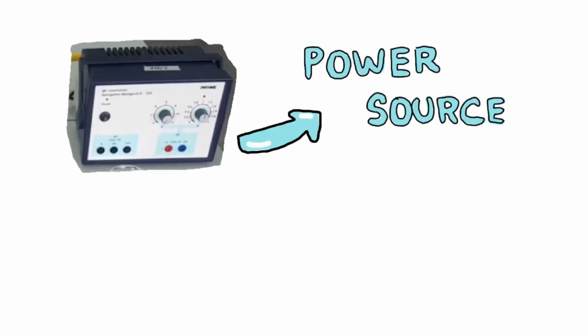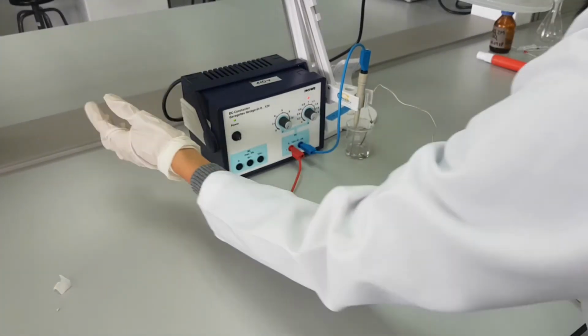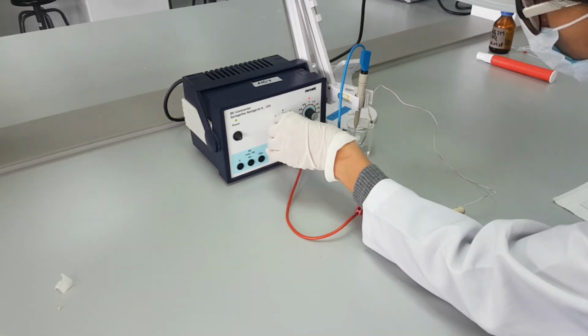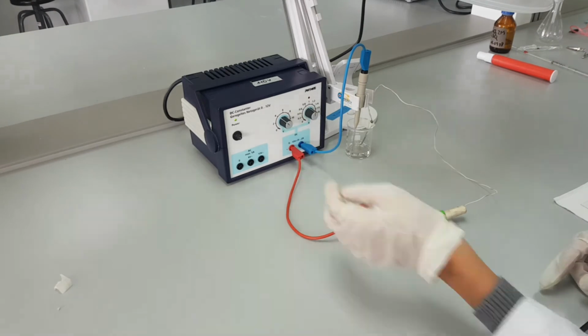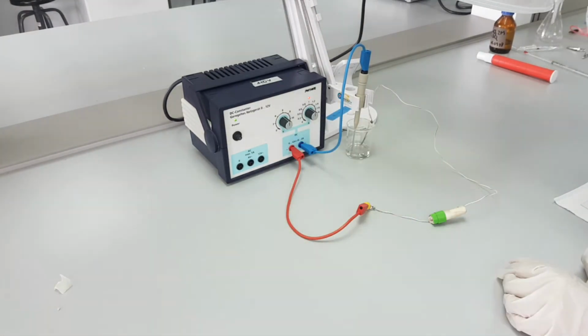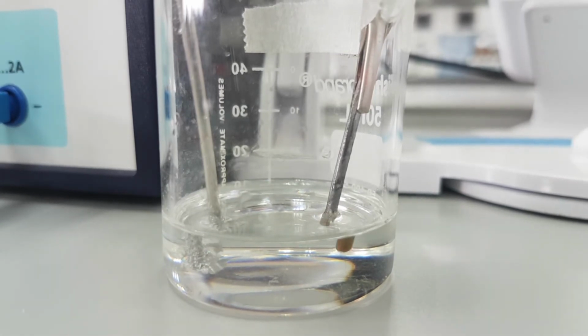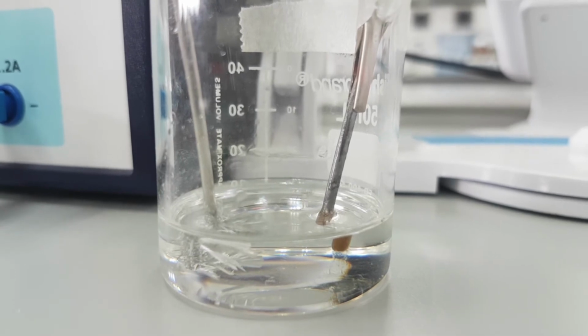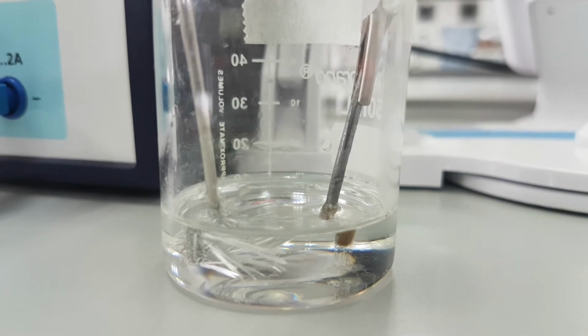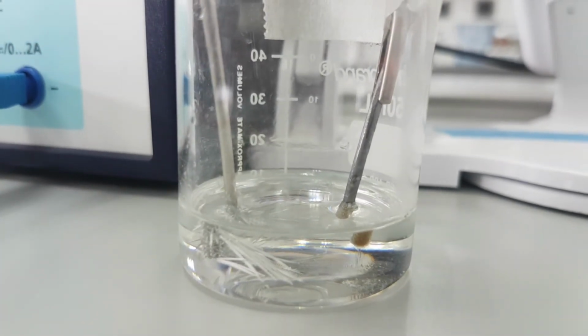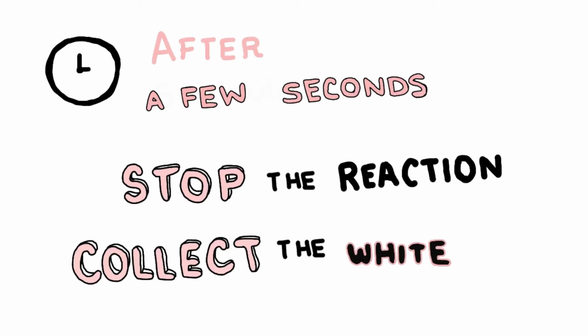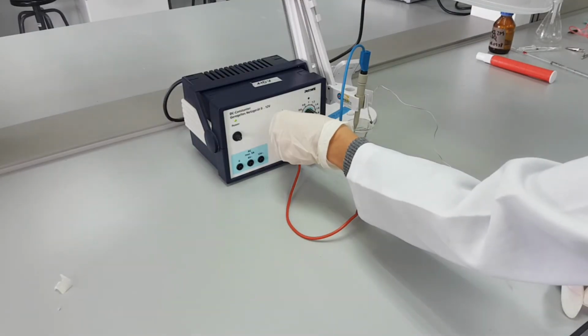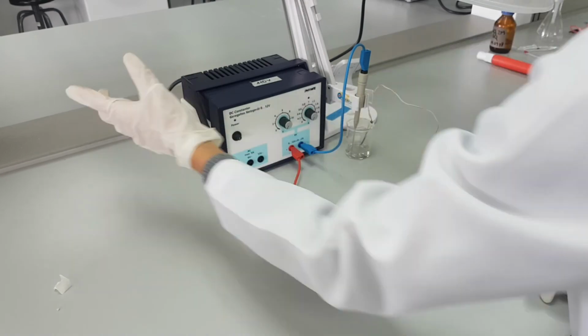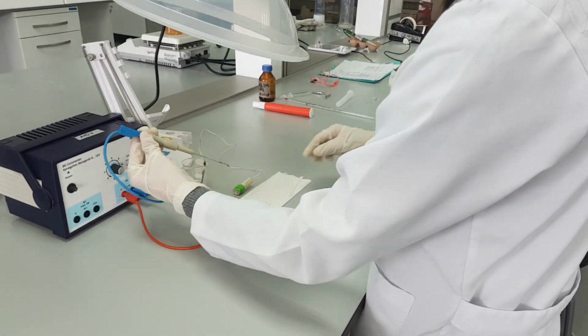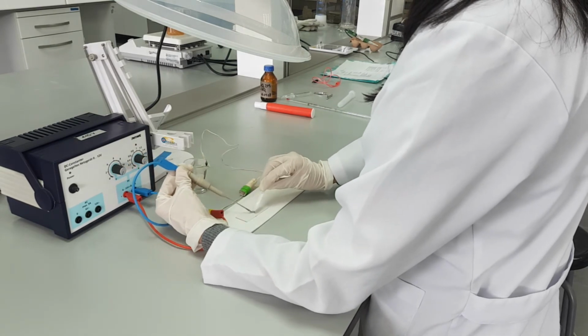We set the values for the power source at 1 ampere and 10 volts, and then we started. Then tin 2 cations travel through the electrolytic solution to the cathode, where they are reduced and deposited on the surface of the platinum electrode. As we see here, the crystallization of tin is happening. After a few seconds of applied current, we stop the reaction, and then we collect the white tin layer formed in the cathode. First, we carefully remove the tin crystal from the platinum wire with a spatula.